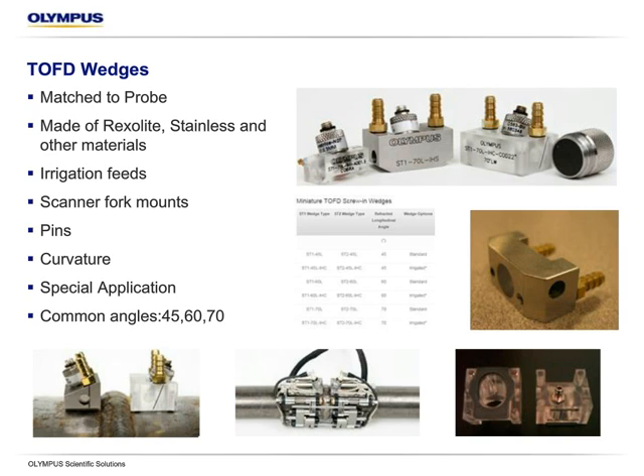Obviously, for curved components, we're going to match that curvature as closely as possible to the component that we're inspecting. And then we have special application type things. The bottom right is actually a wedge made for HDPE pipe. This actually has a water interface and a seal. The reason we do this is because the natural velocity of HDPE and other plastics is too close to Rexolite, so it can cause issues in getting the proper beam propagation. So by using water, we're able to do that very easily and conveniently.